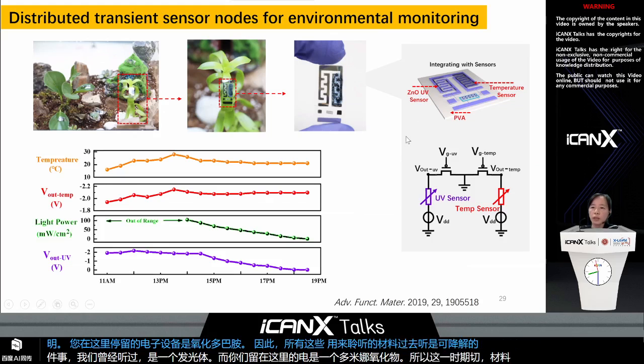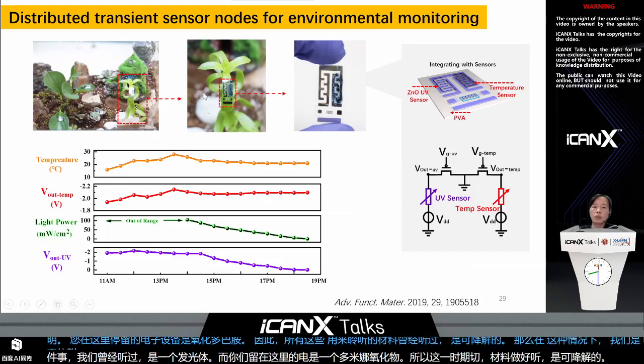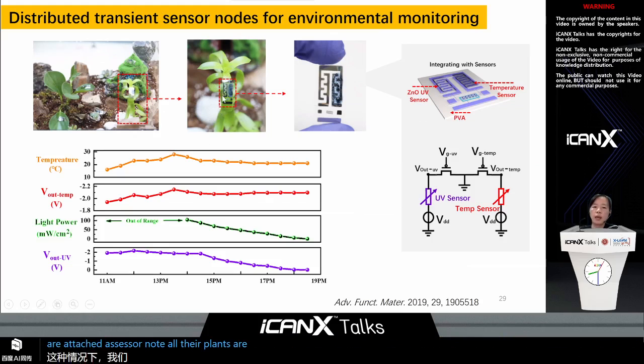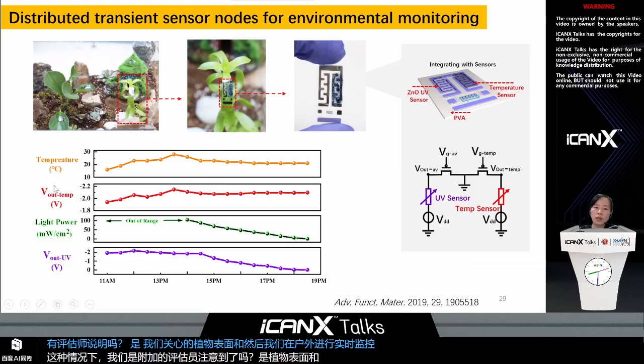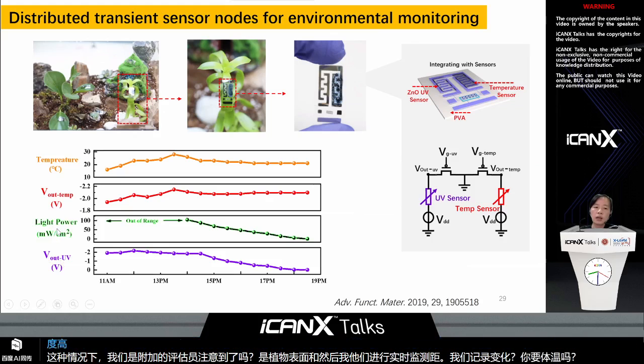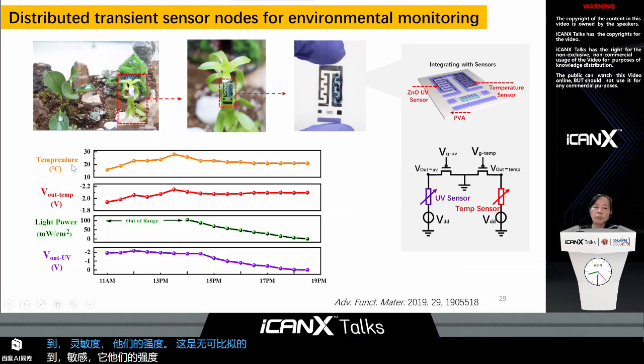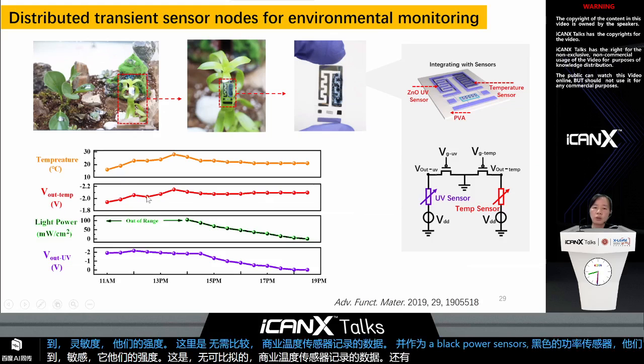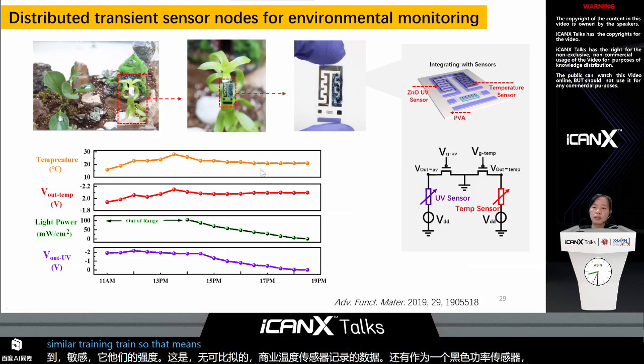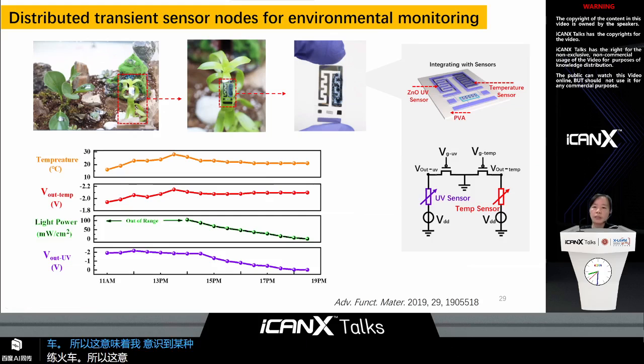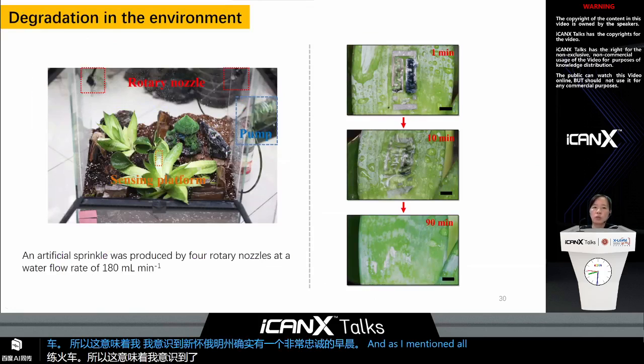So in this case, we attached the sensor node on the plant surface, and then we carried out real-time monitoring outdoors. We recorded the change of the temperature and also the UV light intensity. And here is the result compared to the data recorded by a commercial temperature sensor and light power sensor, and they show a similar changing trend. So that means it realized high-fidelity monitoring of the environment.